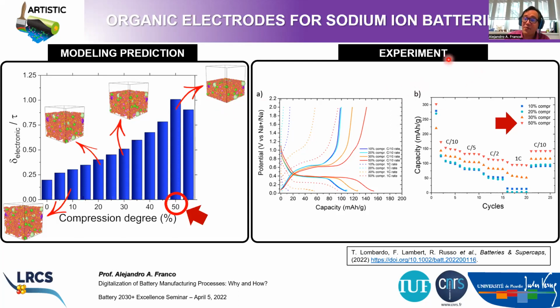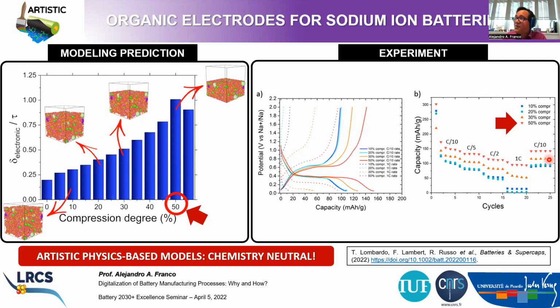What is interesting to see is that we found something very similar at the experimental level. When you make electrodes with different compression degrees, following the same protocol that we have established on the computational side, you see that the electrode with 50% compression degree versus the initial thickness is the one which performed the best. And also from the experimental point of view, we show that it's impossible to make electrodes with this formulation above 50% compression. If you want to compress more, it is not possible. The particles start to crack and you cannot cycle the battery. So this, we believe, shows once again that these artistic physics-based models are chemistry neutral. It is a nice demonstration that we can move beyond lithium-ion batteries, beyond commercial active materials, and we can even move now to organic batteries.